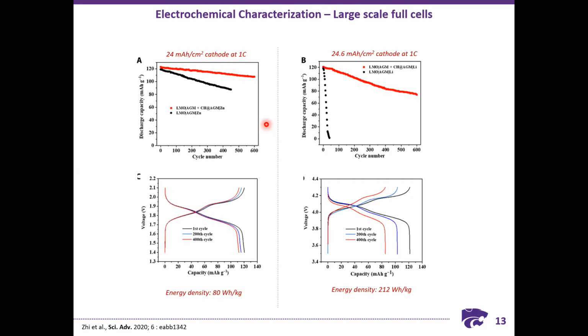So with this too, you can see that the effect is huge between the use of CH at AGM interlayer and without an interlayer. So the red curve, it shows that after it sustained for around 600 cycles, the capacity declined from around 120 milliampere per gram to more than 100 milliampere per gram. So here too, in the case of lithium full cells, the effect is quite dramatic. Without the use of interlayer, at around 50 cycles, the discharge capacity is almost zero, while with the use of interlayer, it sustained for more than 600 cycles.